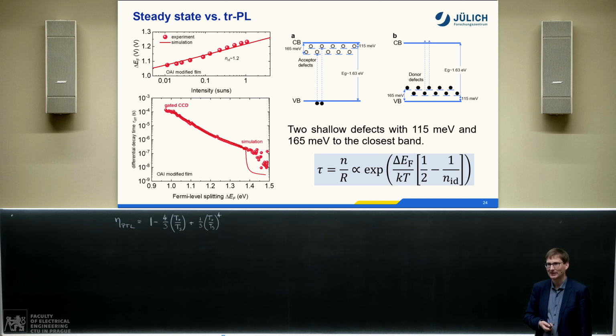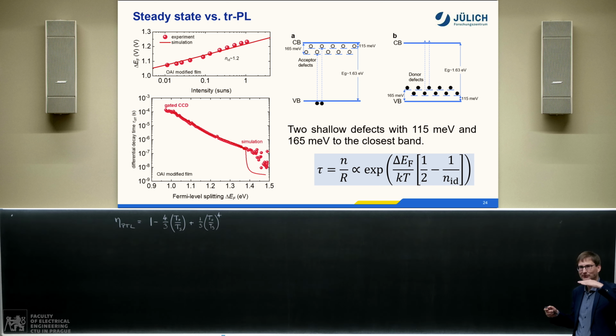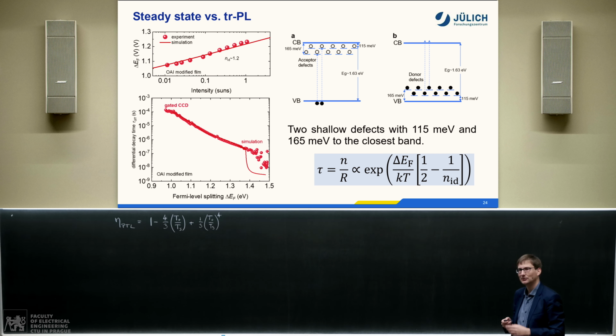So far, so good from a mathematical point of view, hopefully. Now let's assume the idea is just to do a test. If the ideality factor is 2, then we get 1/2 minus 1/2, which is 0. So we get flat tau. This is what I showed you before: deep trap makes it go flat. If we have radiative recombination, it's 1/2 minus 1, which would be minus 1/2. So that's the minus 1/2 slope that I showed you before for radiative recombination.